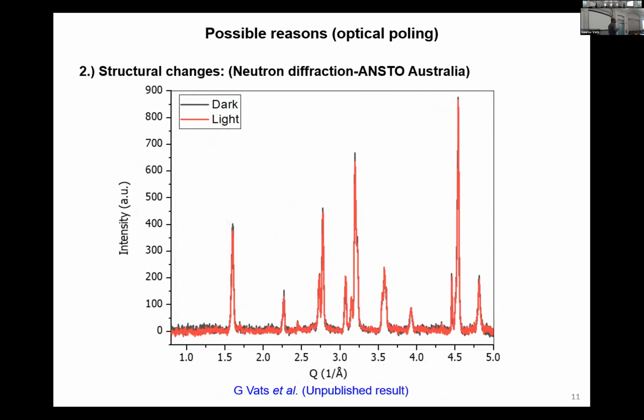structural changes. So what I did is I performed this neutron diffraction experiments at ANSTO in Australia. So I acquired a pattern in dark and another in light when the sample was exposed. And you can see there is slight change in the intensities of a few peaks. Few are going up and few are going down. I mean, we are still analyzing these results, but the problem is either these changes are coming from an error from the instrument, or probably there are no structural changes. Or there is a possibility that structural changes are so small that our instrument could not measure them. So for the time being, we are ruling out this possibility as well.